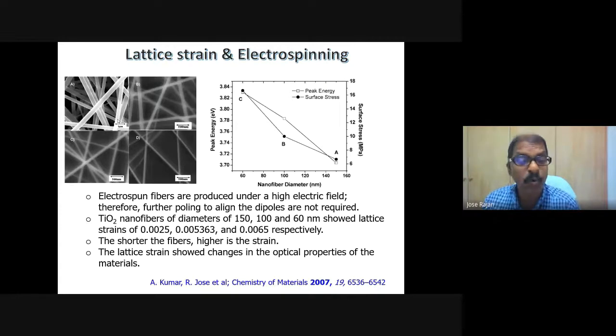So the materials, the narrower, the thinner fibers that we can create, the higher strain it has. When it has an intrinsic strain, it will offer you a much higher piezoelectric coefficient. In this particular case, like what I showed before, we have developed two sets of polymers, PVDF fibers, PVDF and its copolymer. One is aligned. Aligning is by means of controlling its fiber direction using two rings. The details are there in this publication.